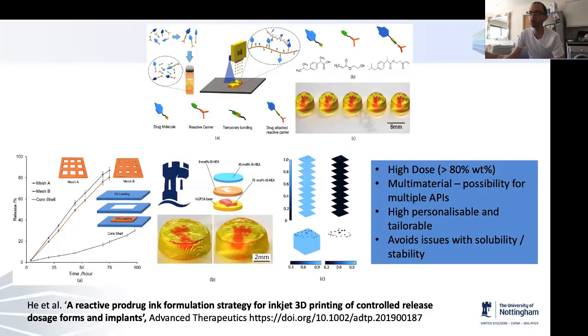A different way of controlling the microstructure we found was to actually covalently bond the drug to the polymer backbone, and this gave us a really strong, intimate and exquisite way of controlling the release, and also a really nice benefit of being able to get a really high dose of drug into our formulation without everything precipitating out and falling out.